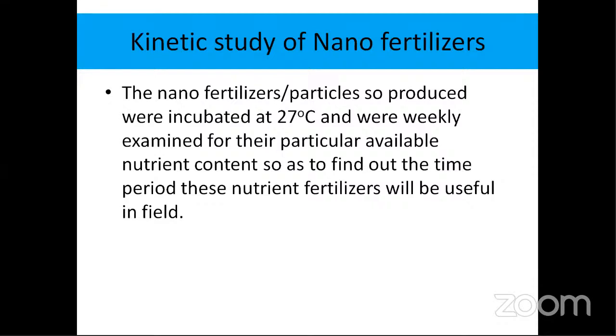Therefore, to find out whether our fertilizer will be able to give something over a longer period of time in the soil system, we had to see the kinetic study. For the kinetic study, the nanoparticles so produced were incubated at 27 degrees Celsius and were weekly examined for their available nutrient. For example, for the nano fertilizer that was loaded with nitrogen, we had to see what nitrogen was coming out weekly.